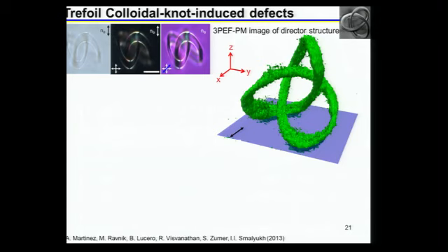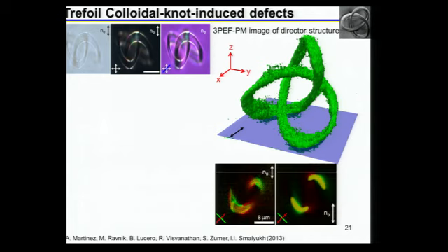conditions. Now, to understand the details of the structure corresponding to it, we can do three-dimensional multi-photon fluorescence imaging of the director distortions around this colloidal particle where director deviates from far-field alignment most significantly. And so that's such an image in here. And then we can look at details of the director structure in each particular plane of interest corresponding to such